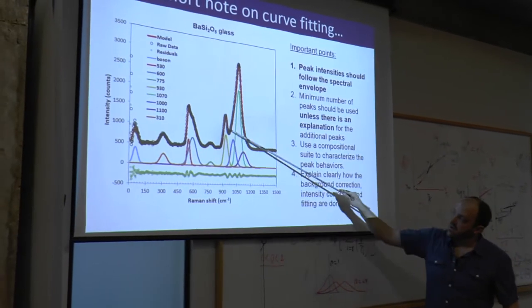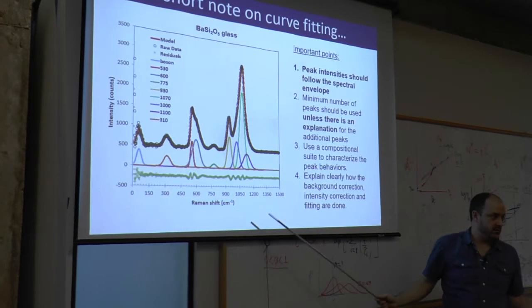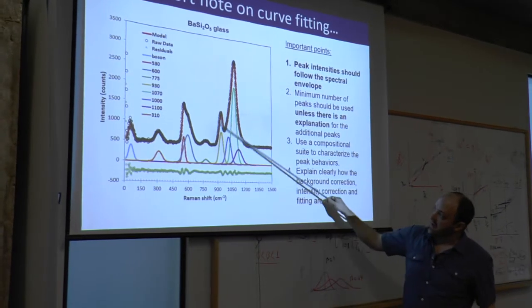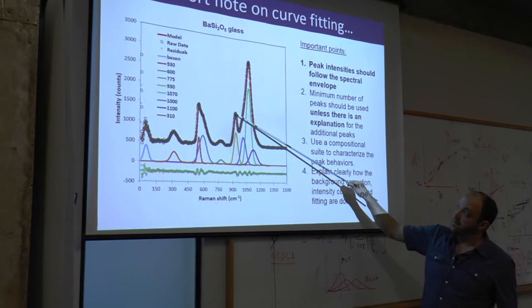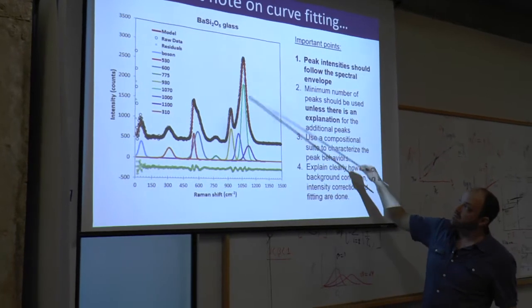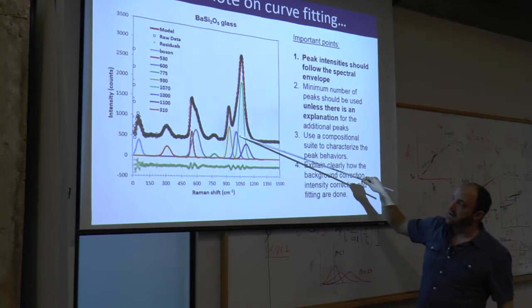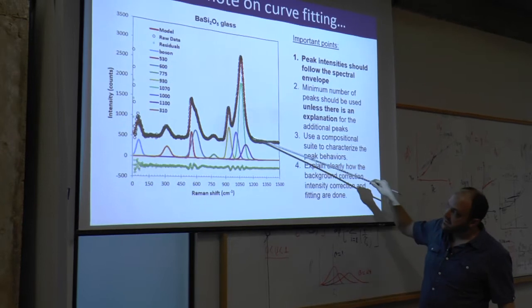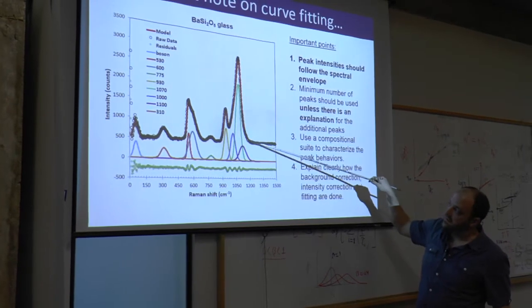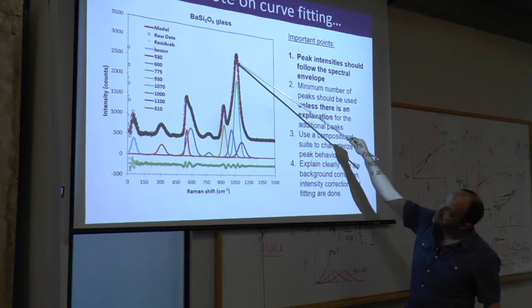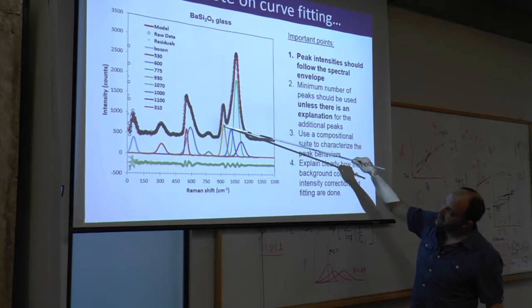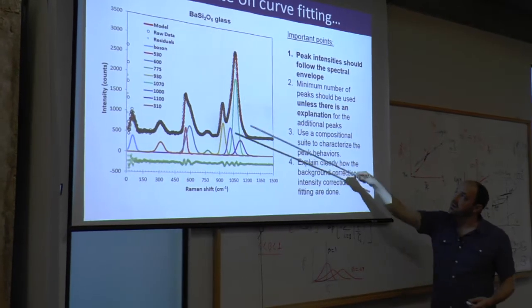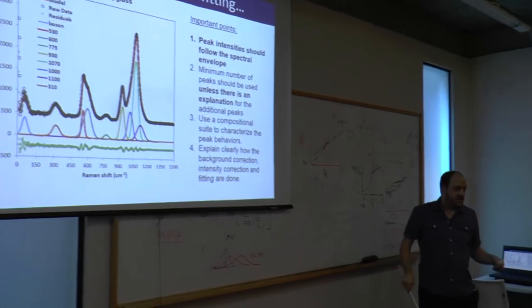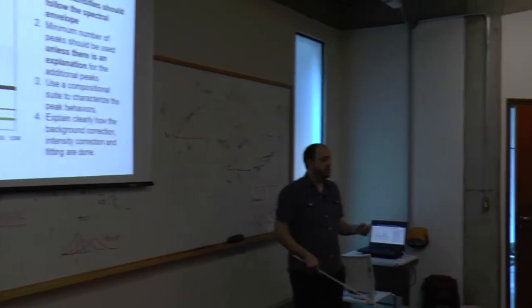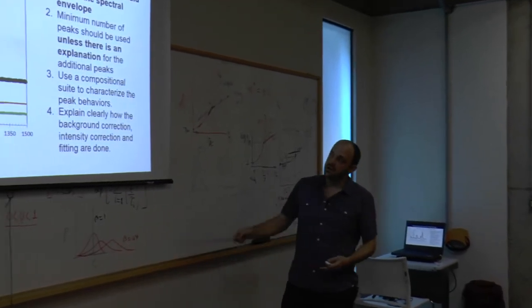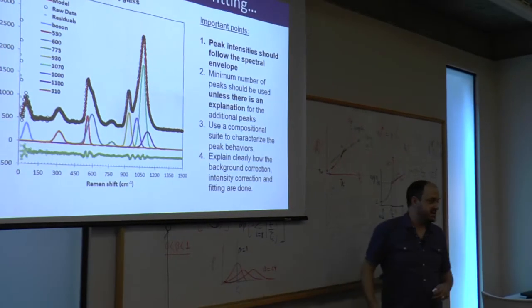The overall shape and number of peaks should mirror the spectra. So we have a nice sharp intense peak down here, we have one that matches it. We have the main peak in the middle here, it matches it. Then we need something else to fit in this shoulder, and if you look closely, there's a bit of an inflection here. We need some other features in there. So bottom line is that the peaks under the curve should follow the relative intensities of the spectral envelope. That's the number one point.